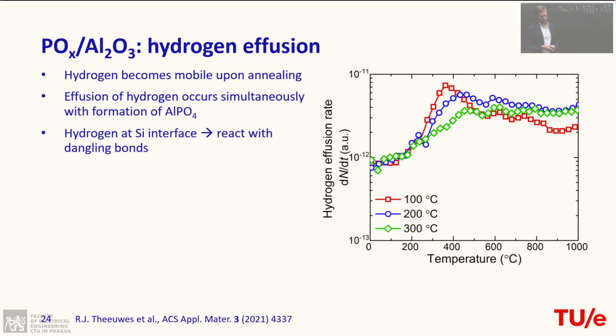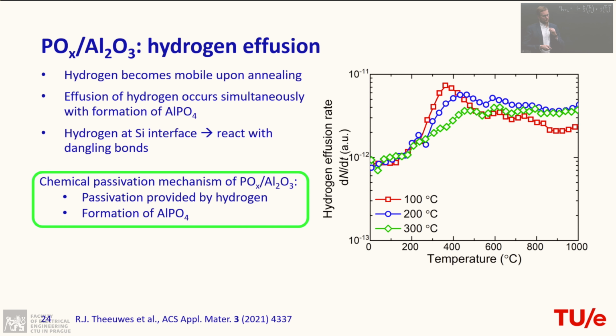Then effusion measurements are also popular in all kinds of thin film investigations, and this is where we see that hydrogen indeed becomes mobile. Here you stick your thin film in a vacuum tube, you gradually heat your sample and measure the hydrogen that's coming out. You're just counting it as a function of temperature. You see that hydrogen is moving because we see a signal has increased over here, and also these so-called effusion spectra are different, meaning that the bonding configurations in your passivation stack are not the same for these growth temperatures. This also supports the fact that we believe that we have hydrogen reaching the silicon interface, meaning you can passivate your dangling bonds there. So, passivation by hydrogen, and you form your aluminum phosphate.